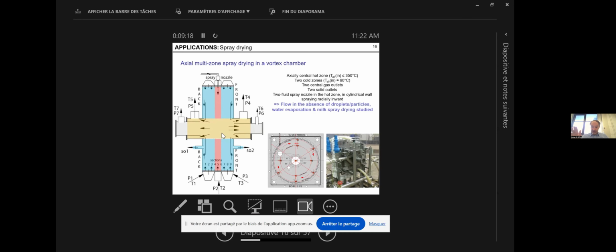because as soon as the particles are evacuated towards the periphery, they can touch the walls and they should not stick to the walls. Or if they are not dry, you will form a paste on the walls. Another thing is that those walls have to be cool enough in order to avoid stickiness of the particles. Yeah? So there are many constraints here that you are facing if you want to intensify spray drying. And so this didn't work, this axial multi-zone drying.